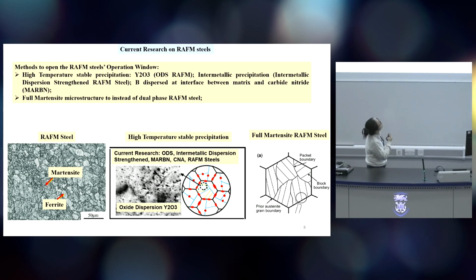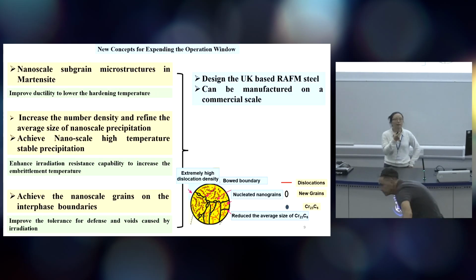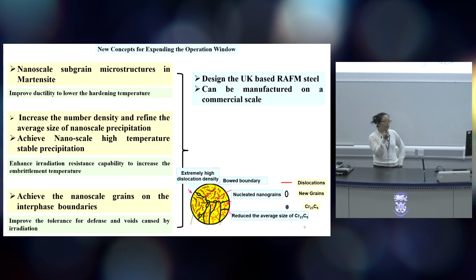But the issue is that we also increase the strength, which will increase the irradiation-induced hardening temperature to nearly 500. So that gives us a question: how can we open the operation window not only for the high temperature but also for the low temperature?